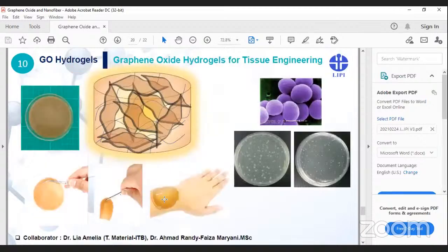And the last for my presentation in application of the graphene oxide, we use it for the hydrogel based on the graphene oxide, and we try to mix the graphene oxide and some hydrophilic polymers and make it into hydrogels by using very easy techniques. We have tried to check the antibacterial activity of the graphene oxide hydrogels by using S. aureus.